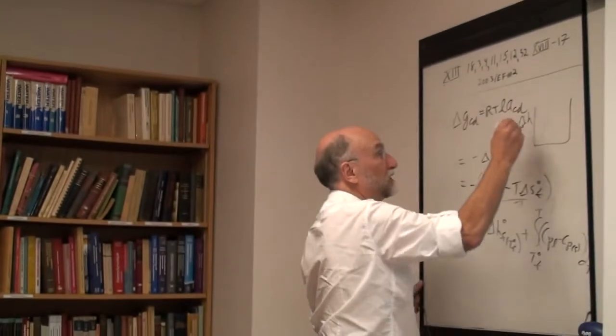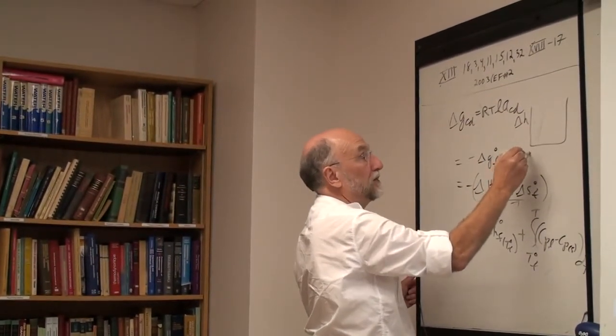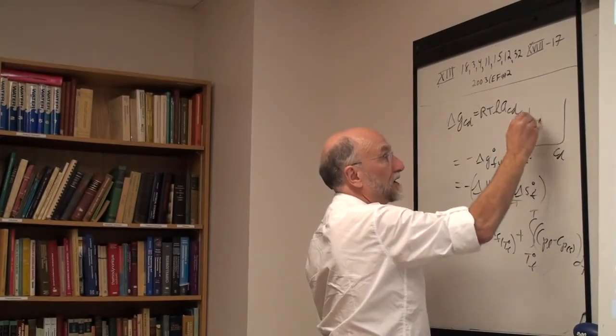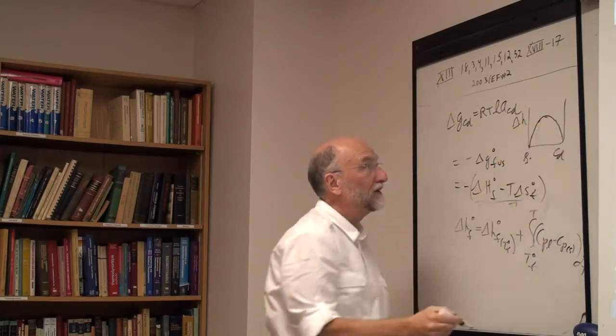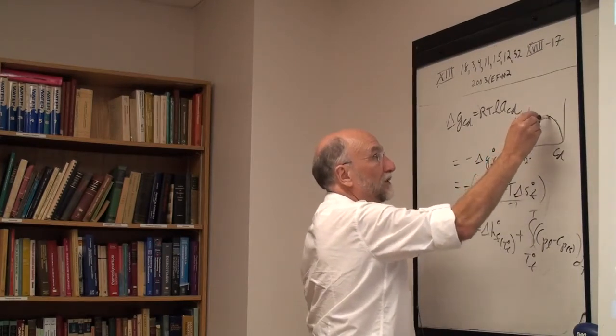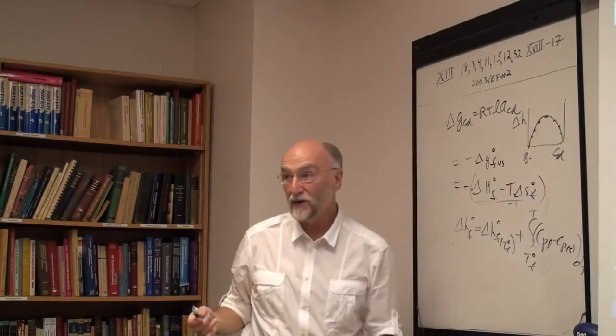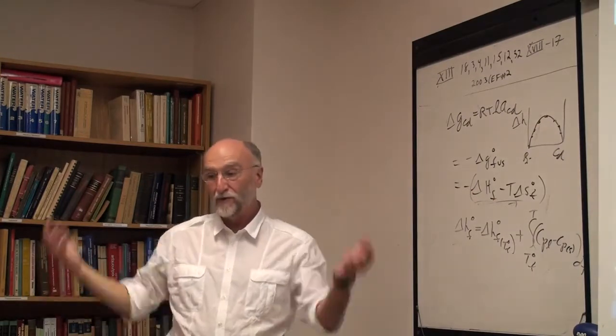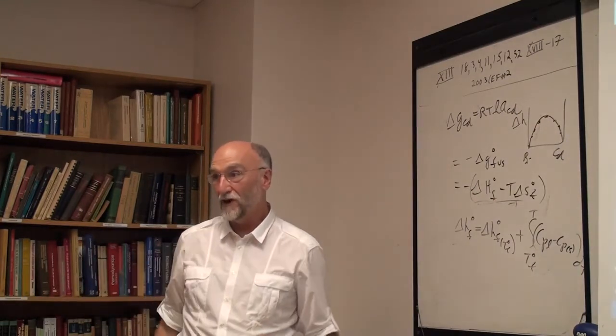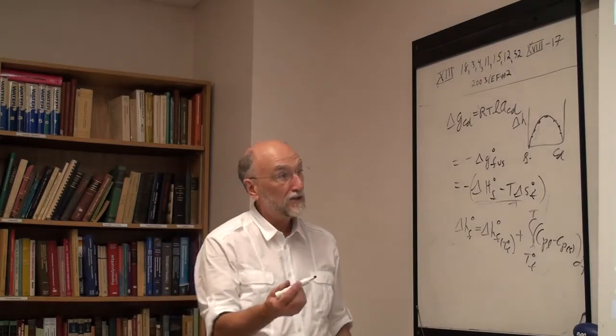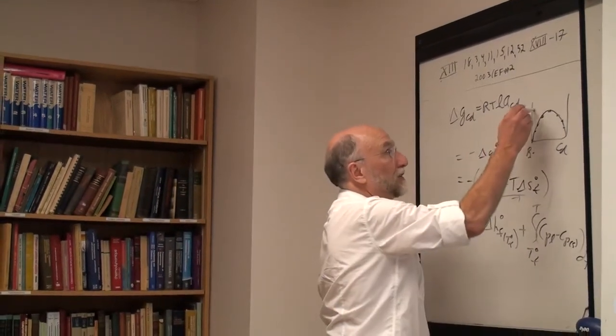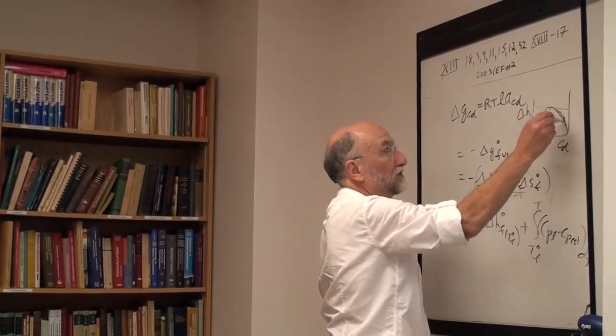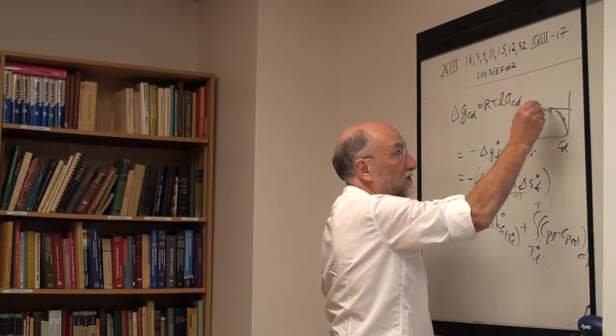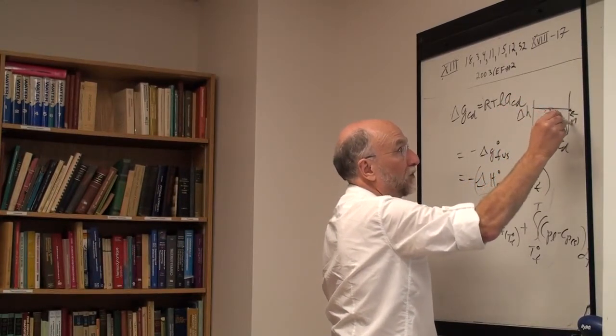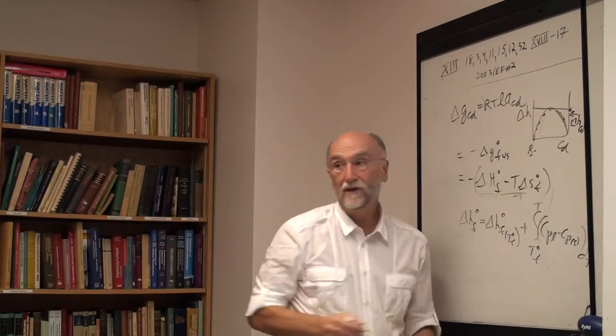This can be measured in different ways, but generally it's measured as a heat of mixing. You go from, whatever, bismuth to cadmium. The heat of mixing is measured in a mixing calorimeter. You get experimental points to measure the heat of mixing in a mixing calorimeter. They mix cadmium and bismuth together and measure the heat that's given off. Okay, heat of mixing, in this case it's positive. And the partial heat of mixing of cadmium, then you measure this curve as a function of composition, take the slope over here, and that point there is the partial heat of mixing of cadmium.